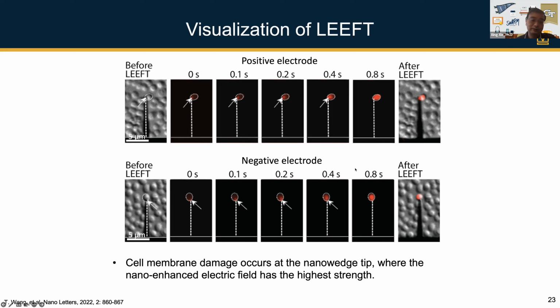So this is the positive electrode, negative electrode. This is also a direct support showing that in this system, the damage of this cell membrane is really caused by the electroporation rather than other mechanisms. Because if it's electro-oxidation or ROS, or other things, the negative electrode and positive electrode would be different, right? And also, if it's heat treatment or other chemical treatments, usually you are not going to see diffusion of the dyes into the cell from just one single point.